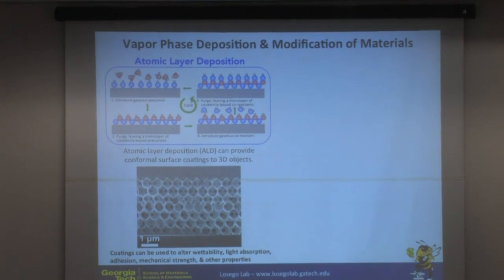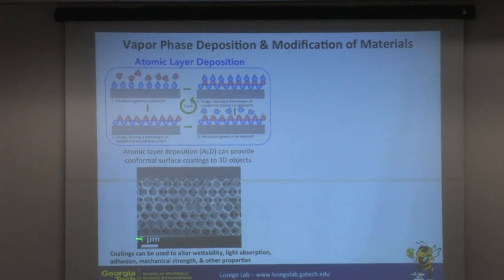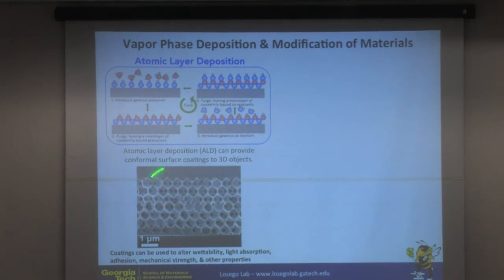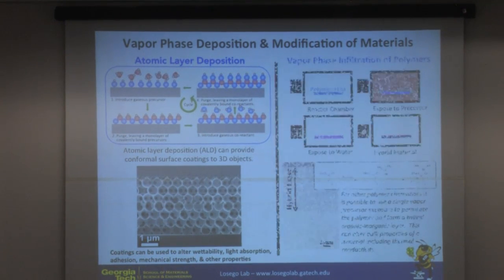So this is an example of a colloidal crystal where we had a bunch of colloidal spheres at the micro scale that had been assembled. We then infiltrated with our gases and did an ALD process to conformally coat those spheres, and then we etched away those spheres. So now the spheres are gone, and we're just seeing the skeleton that's remaining, the photonic crystal skeleton. And so we can use these coatings for a variety of things, including adjusting the wettability of, for example, fabrics, changing light absorption properties, in this case, adhesion, mechanical strength, and other properties.